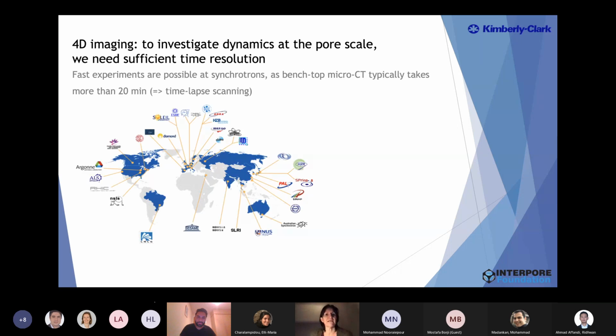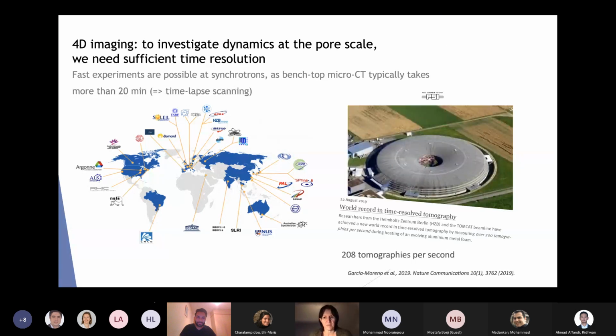Typically what is done is people go to synchrotrons for fast scanning, because with micro CT you often have a scan of about 20 minutes realistically. At synchrotrons you have much higher flux, you get a much faster signal, and you can do very fast CT experiments, even reaching like 208 tomographies per second. Here's a map showing where these kinds of synchrotrons are available, spread over the world.